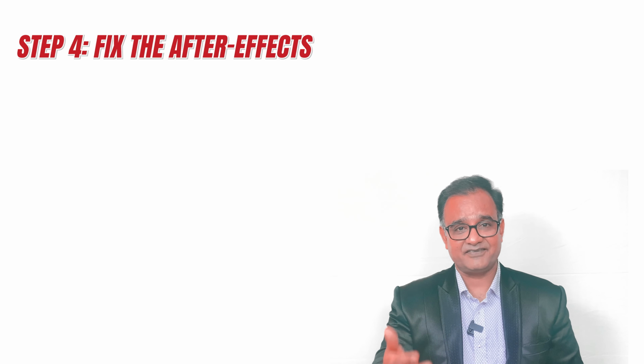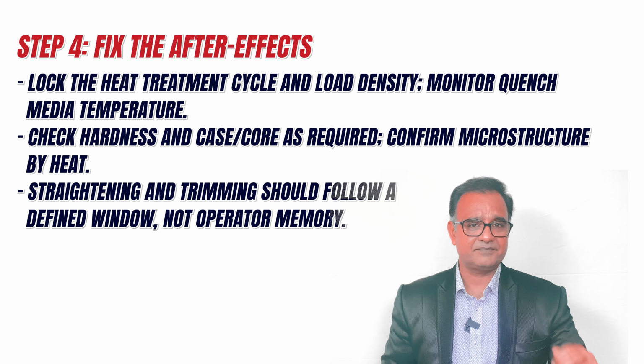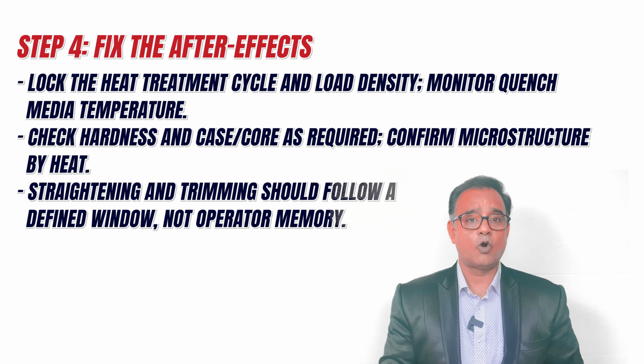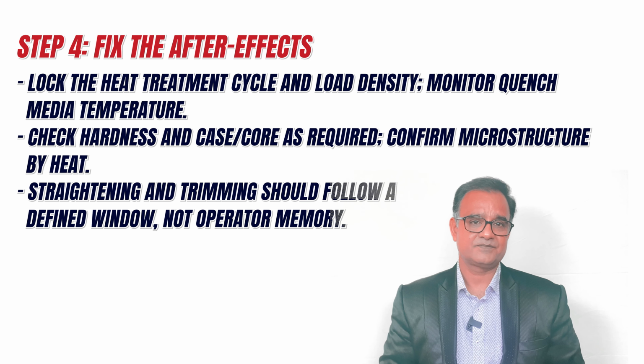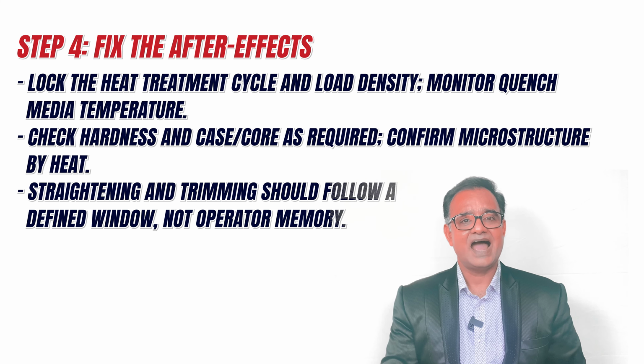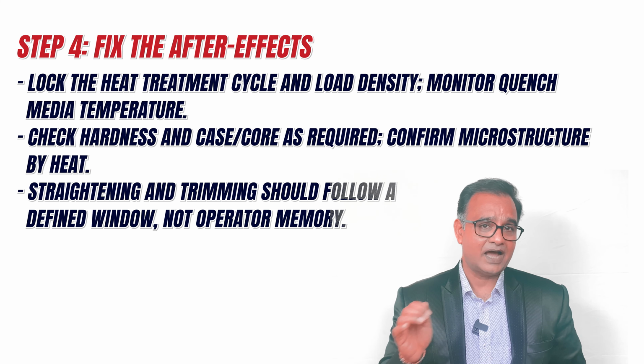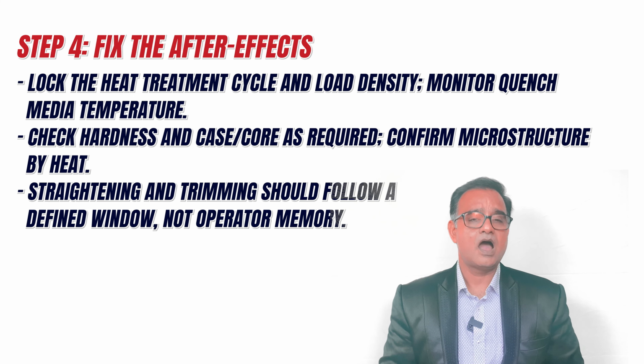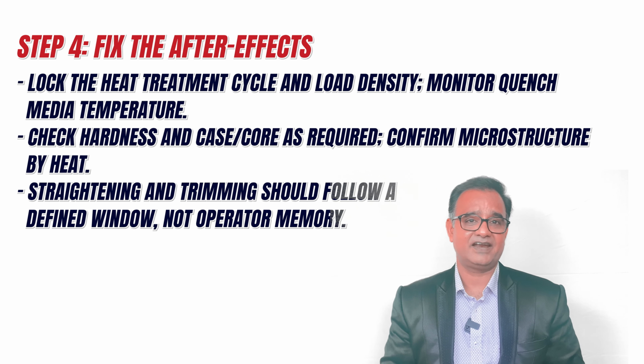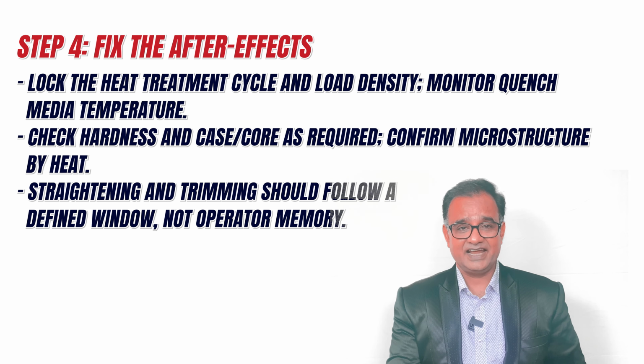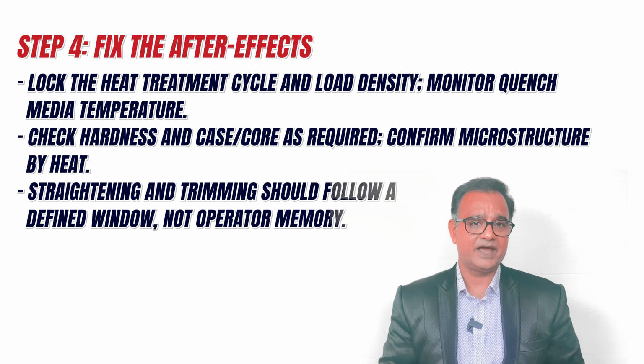Step 4: fix the after effects. Log the heat treatment cycle and load density. Monitor quench media temperature. Check hardness and case or core as required. Confirm microstructure for every heat. Straightening and trimming should follow a defined window, not operator's memory.